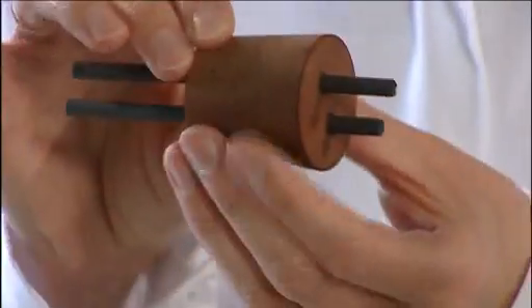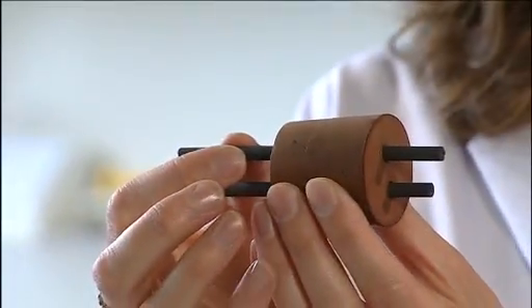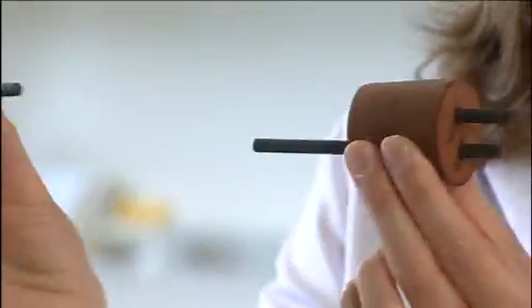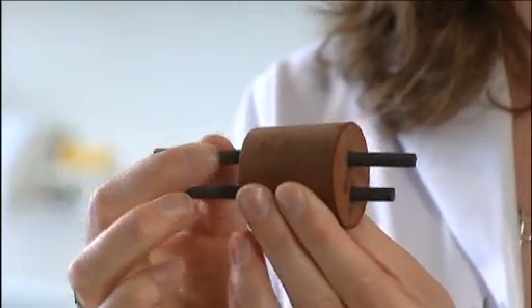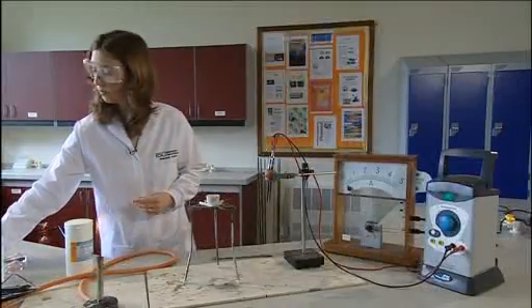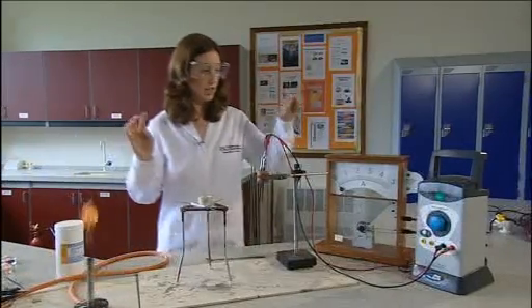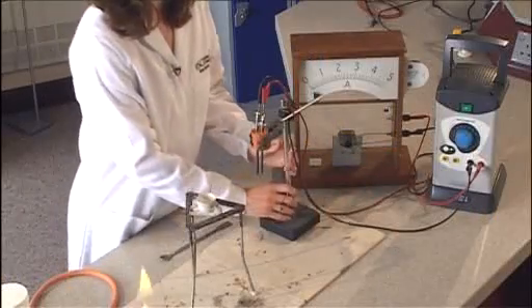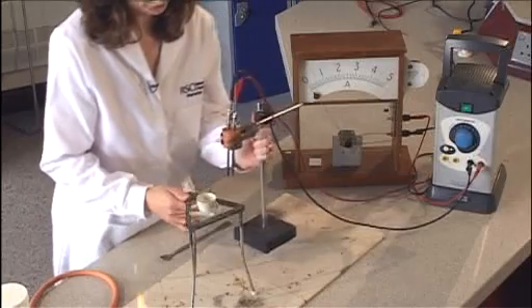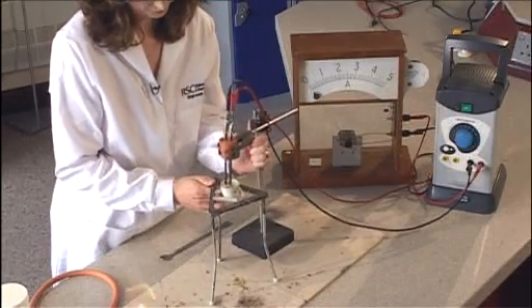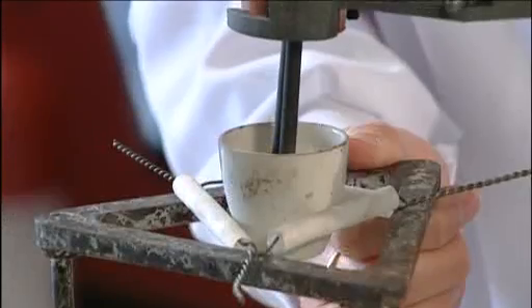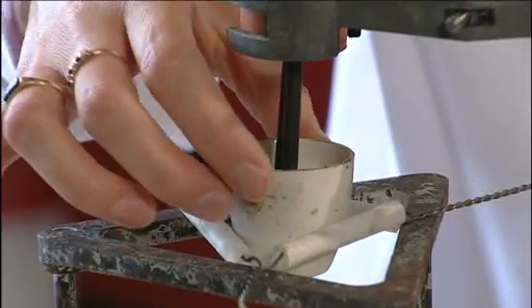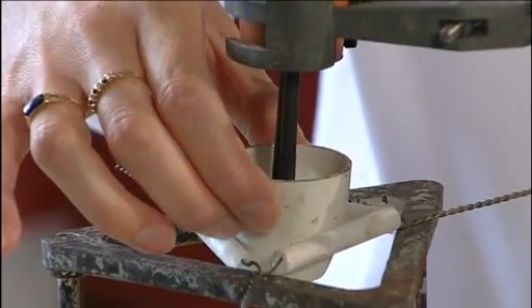It is possible for the graphite rods to crack where they pass through the rubber bung. Suspect this if the circuit does not work and there is no obvious cause. Once you're happy that the circuit is complete, position the electrodes into the crucible. Make sure they go as far down the crucible as possible, but not touching the bottom.